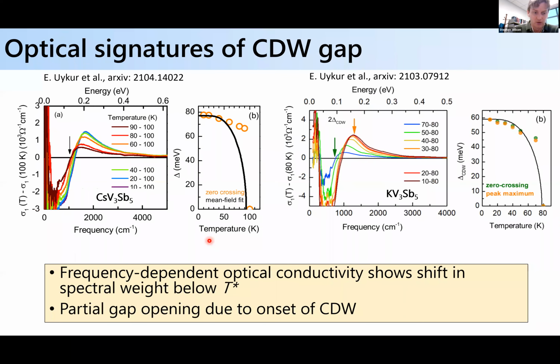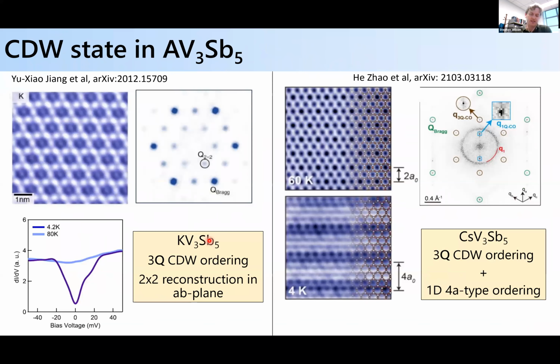Okay. All right. So another probe of the ordering that occurs below T star in these systems, and a very productive probe, has been a number of scanning tunneling microscopy measurements, and I'm just going to highlight a few. So here's from a collaboration with Zahid Hassan's group at Princeton. They looked at the potassium vanadium-3 antimony 5 system, and in the low temperature state, below this 80 Kelvin transition, they basically see a charge texture appear in the local density of states from their tunneling measurements, consistent with charge density wave order. They can do the Fourier transform of this pattern, and then they see these peaks.